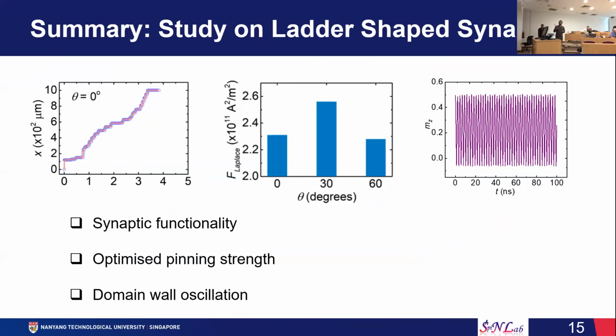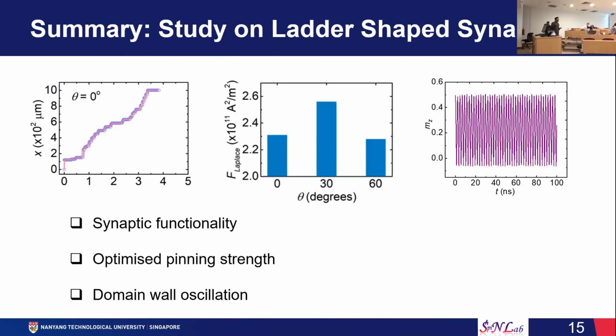And so this is the summary. We achieved the synaptic functionality that was required. We get multiple resistance states. We can optimize the Lorentz force, the pinning state, and we get some sort of oscillation. To wrap up, I just want to mention that we have achieved these types of behavior in micrometer range devices, and if we can get these features in nanoscale also, then that could be a great successful realization.